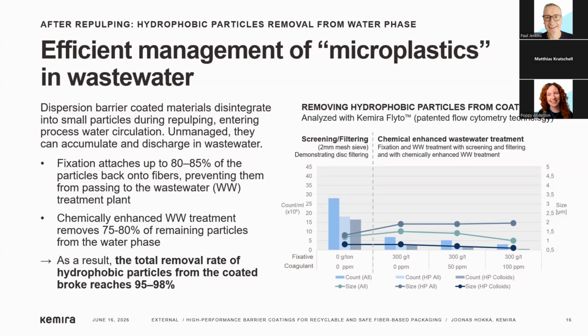This is where chemical expertise makes the difference, as demonstrated in our study. Right fixation chemistry binds particles back onto fibers, capturing around 80 to 85% in the fiber loop. Chemically enhanced wastewater treatment removes most of the rest, combined up to 95 to 98% total removal efficiency. So the important point and bottom line here is, when these particles are actively controlled within the process, it ensures clean water circuits, stable operation, and high recyclability performance.